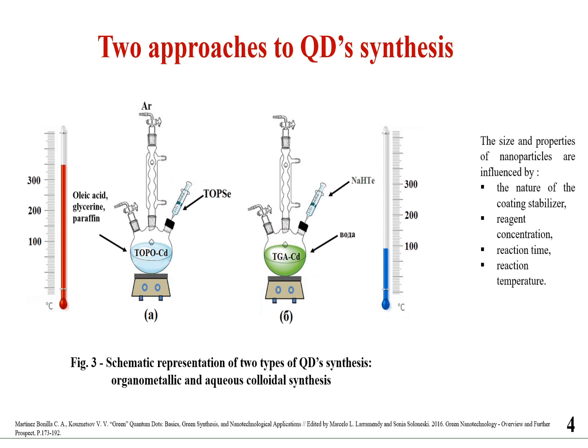There are two main types of colloidal synthesis: aqueous and high-temperature metalorganic. Quantum dot metalorganic synthesis consists of high-temperature injection of precursors into a solution of non-polar organic solvent. The advantages of this method include a small variation in the size of the quantum dots, as well as the high intensity of the luminescence. However, it's also worth noting the relative complexity of this method and the toxicity of the reagents necessary for its implementation, which obliges the synthesis to be done in a well-equipped room using personal protective equipment.